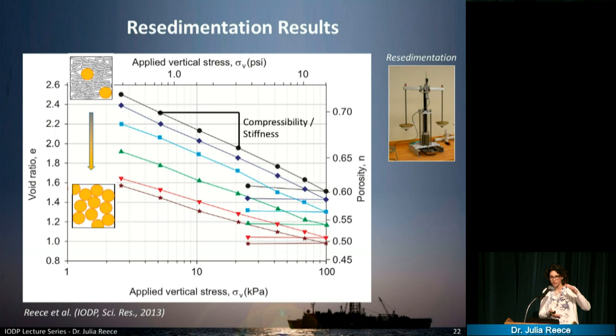And so what you see is that all of these curves show a linear behavior on this semi-logarithmic plot, and all start out with very high porosities and then go down to low porosities. And the slope of this line is this parameter stiffness, like how strong the spring is, how strong the sediment is. And you can also see that the slope is changing slightly, but more significantly, the initial porosity is really changing here.